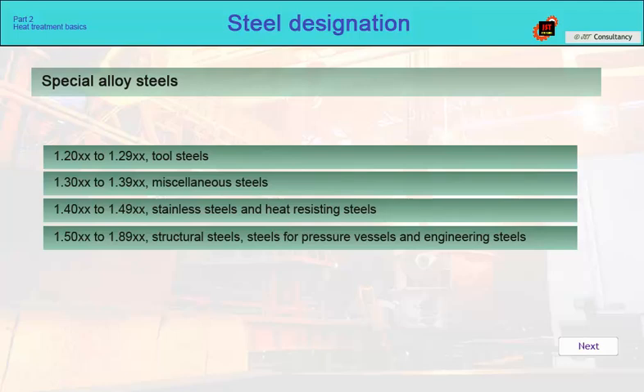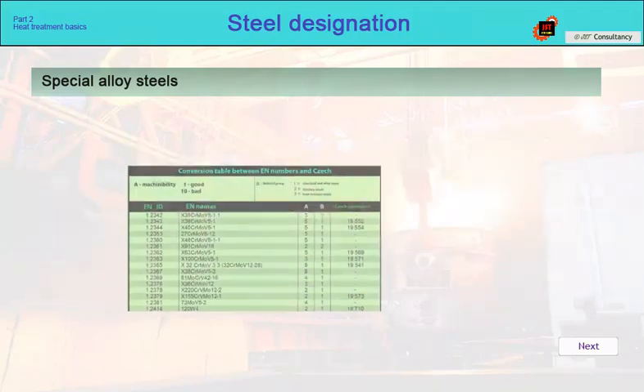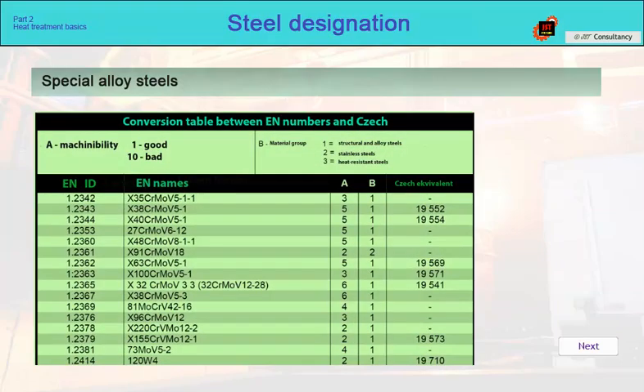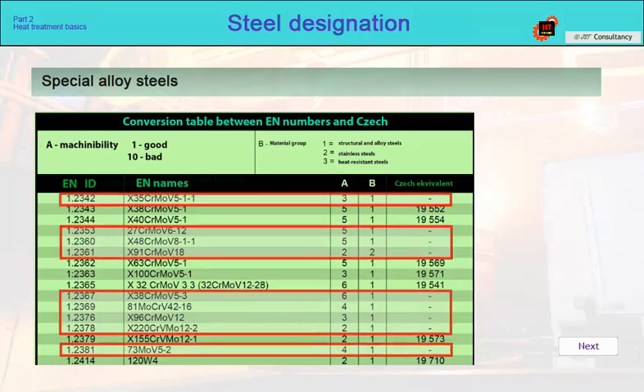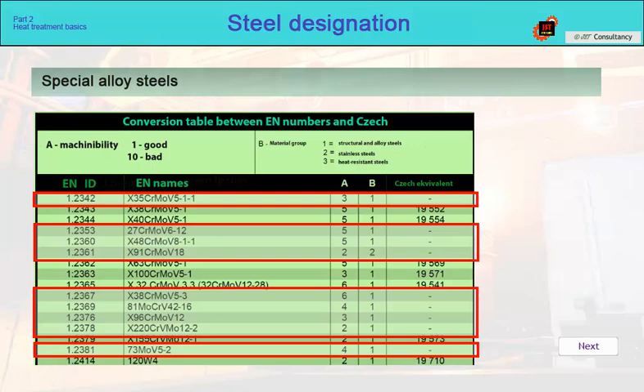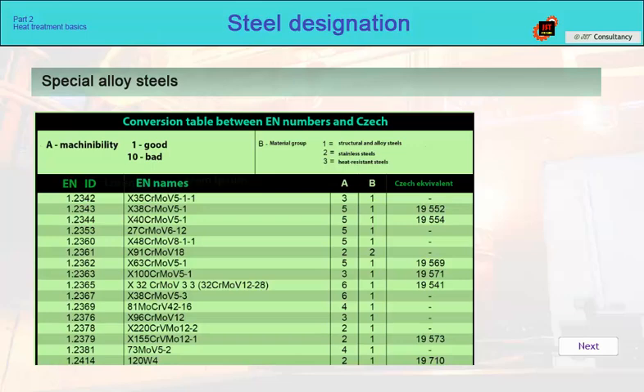In case of replacing the prescribed steel designation with a national standard, non-conforming behavior and non-conforming heat treatment results cannot be excluded. An example can be seen in this table, where for a number of steel grades in Czech national standards, there is no equivalent at all. On the one hand, it is a consequence of the historical development of steels in a given country. On the other hand, it is evidence of the continuous development of new steel grades, with designation according to EN, which will never have an equivalent according to national standards that have been cancelled in the EU.